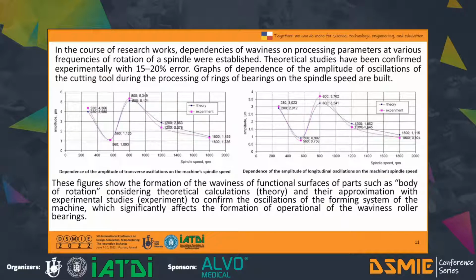In this slide you can see the dependence of the amplitude of transverse oscillation on the machine spindle speed, and the dependence of the amplitude of longitudinal oscillation on the spindle speed. This figure shows the formation of the waviness of the functional surface of parts such as bodies of rotation, considered by theoretical calculation and approximation, which experimental studies confirm: the oscillation of the forming system of the machine significantly affects the formation of waviness of roller bearing rings.